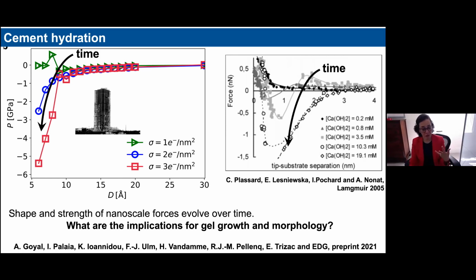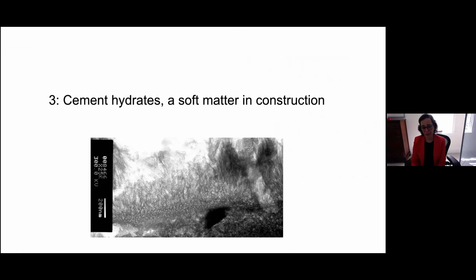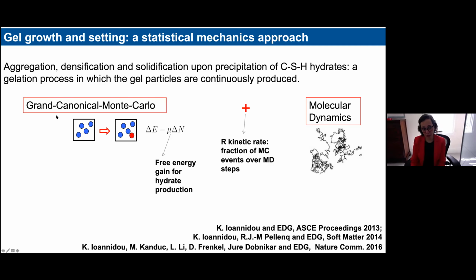Now, how does knowing these forces and understanding this evolution of the cohesion of the material affect the formation of the CSH gels? What we have done is to design an approach in which we can study the development of these CSH gels in a soft matter, coarse-grained type of approach, in which we model the CSH nanoparticle precipitation with a grand canonical Monte Carlo type of process, where the chemical potential, you can think of it as the free energy gain for producing one of these cement hydrate nanoparticles during cement hydration.